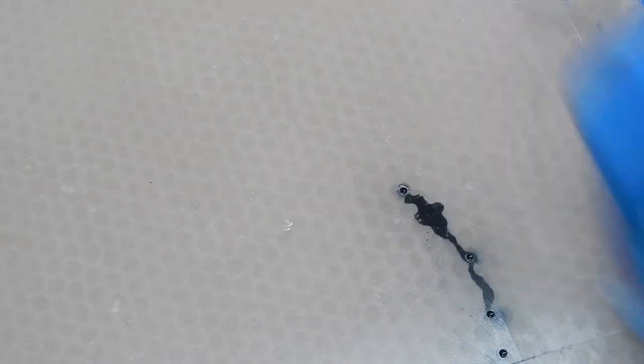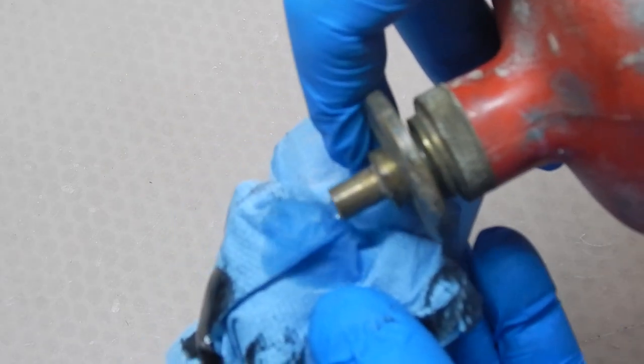And again it would have been nicer to use more core bedding putty and more pressure to get this problem to not happen in the first place. But that's a pretty solid way to glue it back together. This works on bigger voids. And it's just an example of how to do it getting it a little cleanup with acetone.